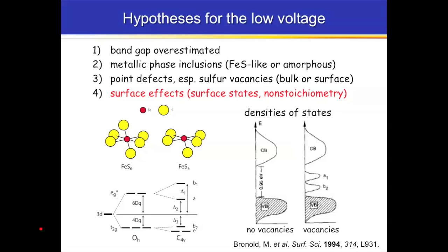Why is the voltage low? Well, this is an area of a lot of debate, and there are a few hypotheses, and I just list several of them here. The first hypothesis is that the band gap has been overestimated, and we've looked into that in detail, and we believe that that is not the case, and so we believe the band gap, in fact, is 1 electron volt or so. The other idea is that pyrite is never phase pure. You can argue against that just by looking at the very high EQE of some of the single crystal pyrite materials that have been made. Idea 3 is that pyrite has a sulfur vacancy defect that's present within it, either at the surface or especially in the bulk.